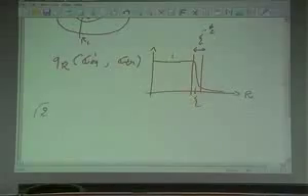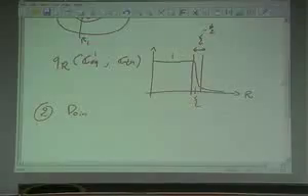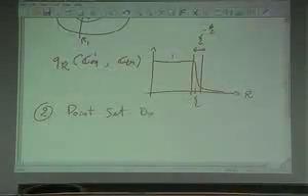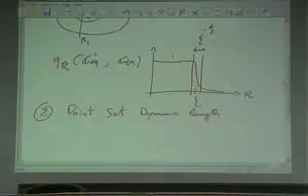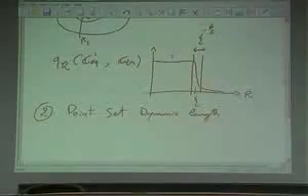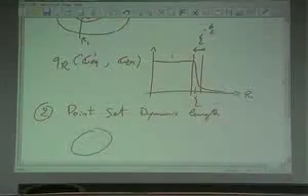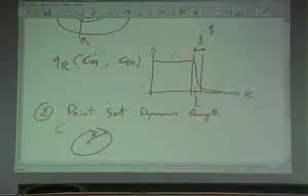And then the second thing, which I would call point to set. I call this the point to set static length, and I will define a point to set dynamic length, which is exactly the same, but it concerns the time scale. So I do exactly the same experiment. I freeze the boundary condition outside in an equilibrium configuration, but now I look at the relaxation time of the system inside the cavity. So I always have my cavity with radius R, and here the configuration frozen.